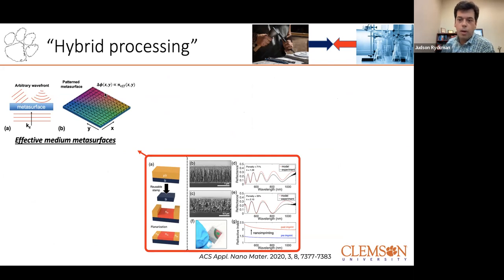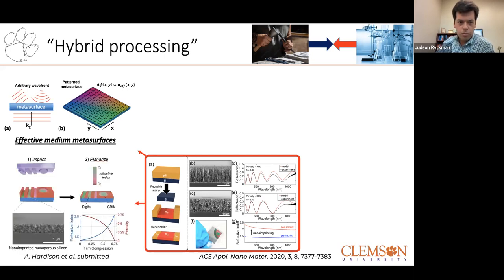And traditionally, this is done by some structural change or size of a pillar or meta atom. But in our case, we could do it in a very smooth or digital fashion by simply changing locally the refractive index. So it is possible with our process to pattern the refractive index potentially with a high spatial resolution and high contrast. And so we have some recent work where we explore this capability. This is currently work that's been submitted. So we demonstrate digital and gradient refractive index patterning.